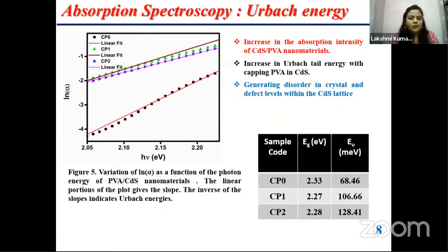And here I have also given the value of band gap. So we can say that after capping, they are somehow generating disorder and defect levels within the crystal lattice, which is the main reason for the increase in Urbach tail energy. To get more insight into the defect levels and disorders in the CdS lattice after capping, we have